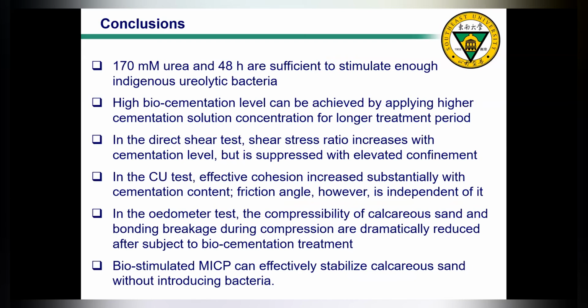Okay, so these are the mechanical performances we obtained from the series of tests, and here are the main conclusions. Firstly, we find that 170 mM urea and 48 hours stimulation time are sufficient to stimulate enough indigenous ureolytic bacteria. Secondly, we find the high biocementation level can be achieved by applying higher cementation solution concentration and a longer treatment period. And thirdly, in the direct shear test, the peak shear stress ratio increases with cementation level, but is suppressed with elevated confinement. Then in the CU triaxial shear test, effective cohesion increased substantially with cementation content. Friction angle, however, is independent of it.